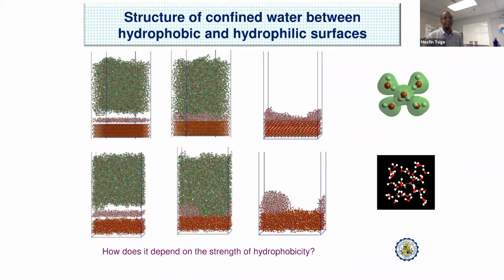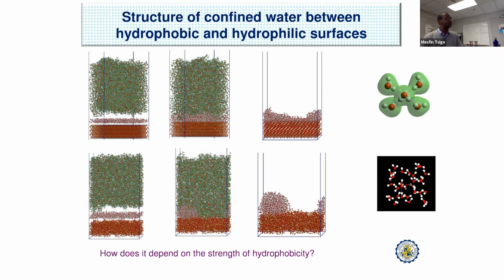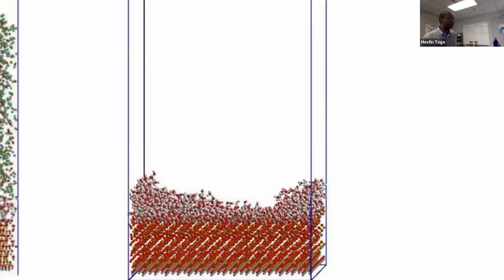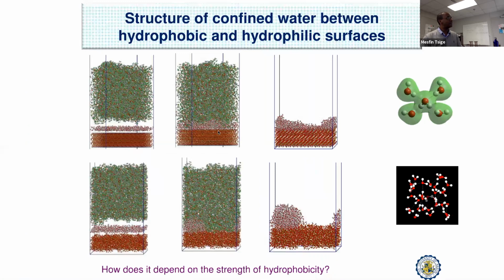And it is hydrophilic, which means it has, in this particular case, about 9.6 OH groups per nanometer squared on the surface. So I have hydrophilic, hydrophobic. When I contact and equilibrate the system, we see that the structure of the water has significantly changed. If I show you closer, here I have the substrate. What happened is that the first layer close to the substrate is okay, but the second layer peels off and forms more like a hemispherical cup in between the PDMS and the alpha quartz.